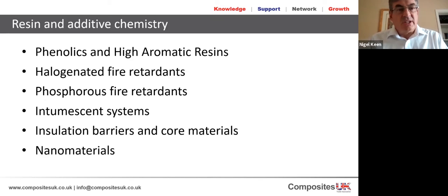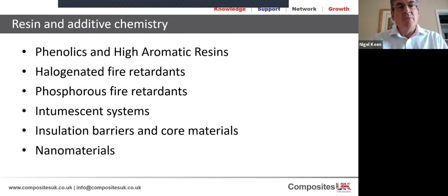When we're talking about the matrix systems and the additive systems, certain chemistries lend themselves very well in fire. Typically resins that are fire resistant have a very high aromatic content. It means that when they burn, they tend to form quite a solid char. They have a high char content. The carbons in the organic structure form into ring structures. They produce graphitic structures that are themselves quite fire resistant. So phenolics are very difficult to ignite. They might smoke a little bit and they'll form a char, and that char is itself fairly flame resistant. And we've seen quite a lot of other things come forward. Some of the benzoxazines, some of the furanes and furfuryl alcohols have a similar way of resisting flame, and they're being used quite widely now.